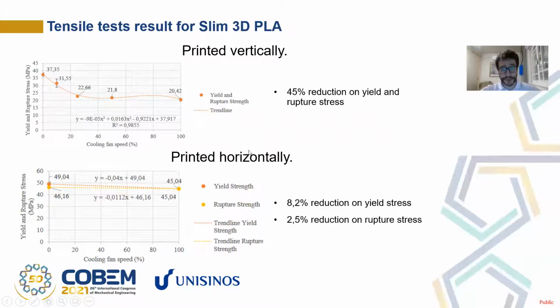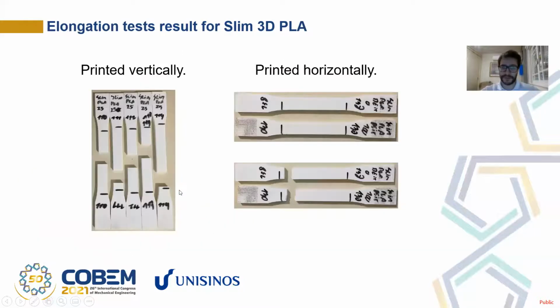For the ones printed horizontally, with the cooling fan turned off, the reduction was around 8.2% on the yield stresses, but it had a different point for the rupture stresses, as we can see here, a little bit lower. So it starts to deform and form a neck, then rupture. And for the ones manufactured with the cooling fan at maximum, it was the same thing. It broke at the same point.